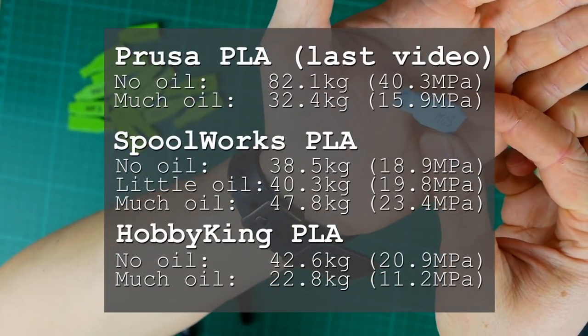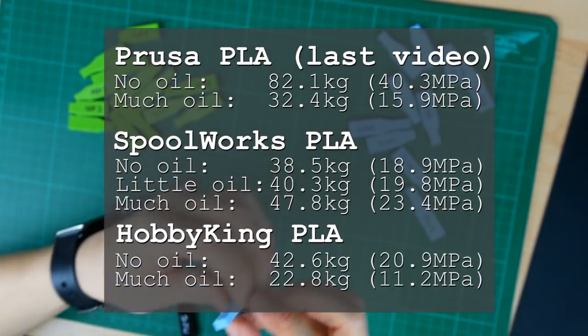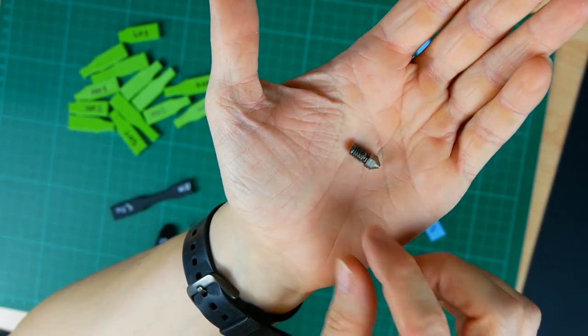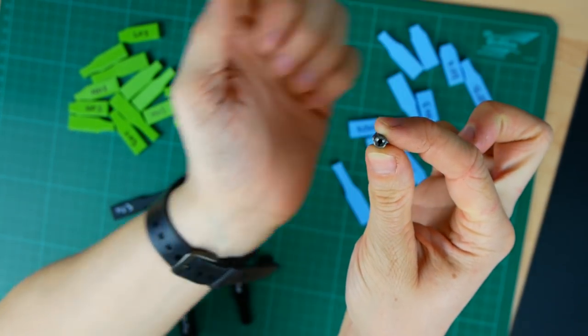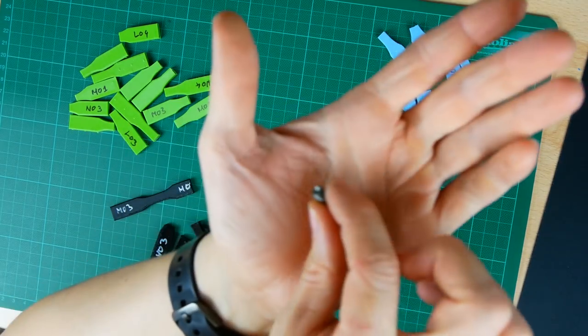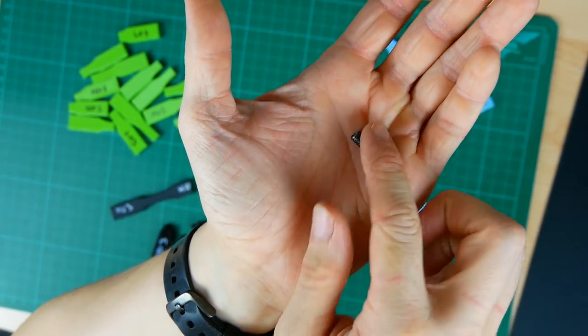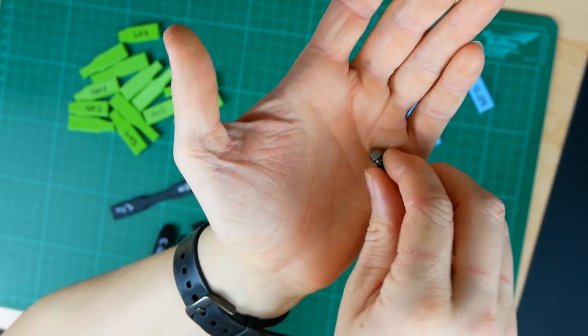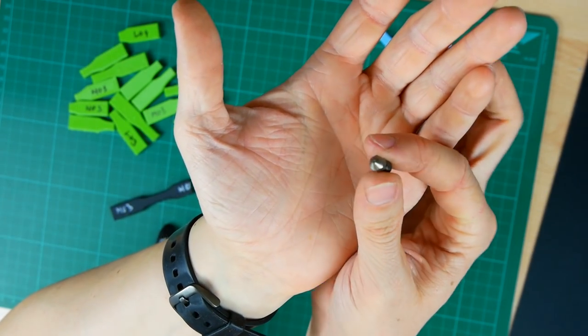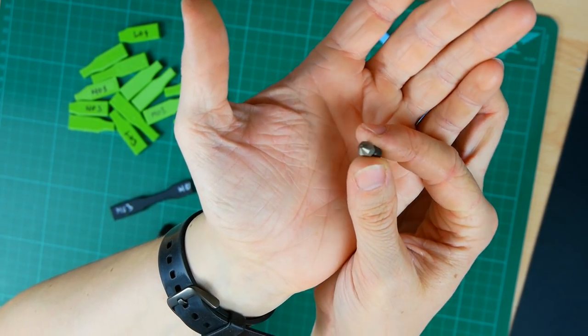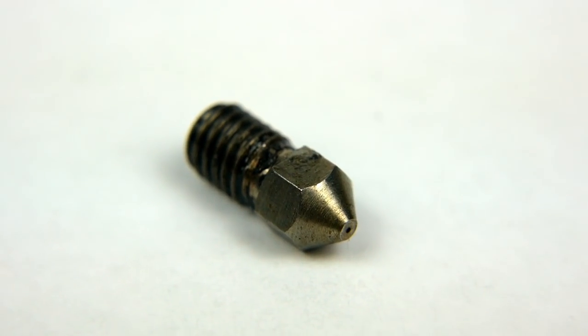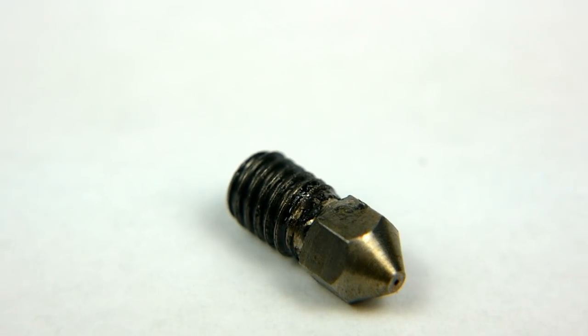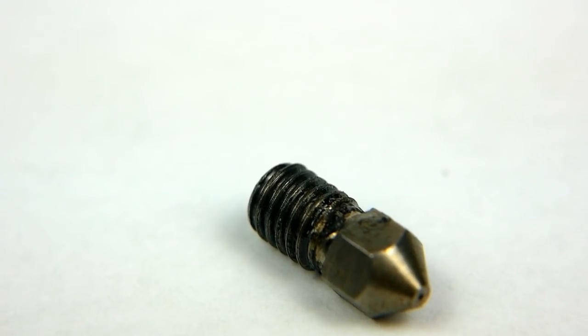Still the overall results were way worse than in the first test. I realized that I had been using the new tungsten nozzle for the prints which already caused problems in other prints. Before I mounted it in my printer I had been looking at the nozzle under my microscope and the surface finish on the inside wasn't really nice. Lots of machining marks. Also the bore in the nozzle is not perfectly in the center and I noticed that I often had lots of filament stuck to it.